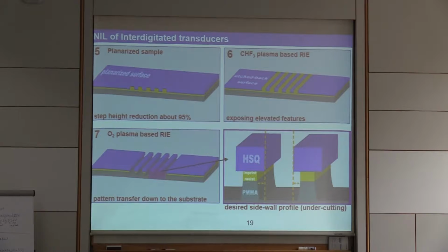If you now continue with an oxygen plasma, you only make the HSQ more resistant, because you even further oxidize this HSQ, but you remove the organic material. And the reason why that is very nice for us is that we can keep the critical dimensions of the imprint, because they are determined by the initial imprint, and therefore also finally by the width of this HSQ feature. So now again the reverse. But this plasma etching is now non-critical while maintaining the critical dimensions, and even more so we can over-etch a little bit in this oxygen step and get an undercut. So those are two features which are very important, we think, for maintaining the critical dimensions.